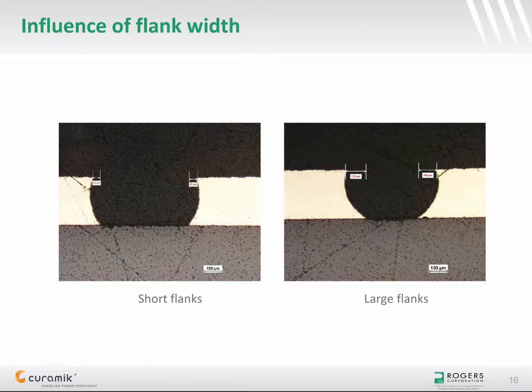Another parameter that has an influence on reliability is the etching ratio or etching flank width. For one and the same copper pattern according to drawing, one might increase or reduce the etching time to guarantee that the distance between copper tracks will be sufficient for the purpose of electrical isolation. For thick copper metallization, as opposed to thin layers of copper, a steep or tapered etching flank can hardly be achieved even if you would reduce the etching speed and increase the etching time. Anyway, etching the parts longer may not be a good idea.